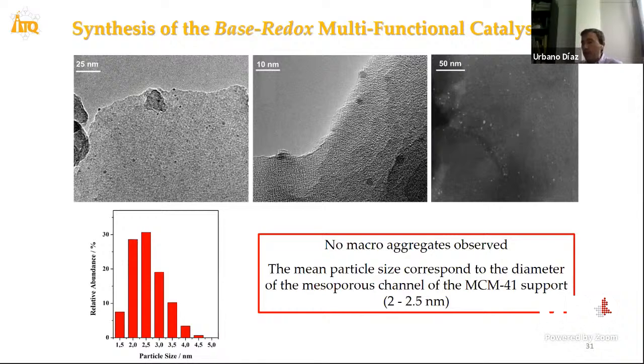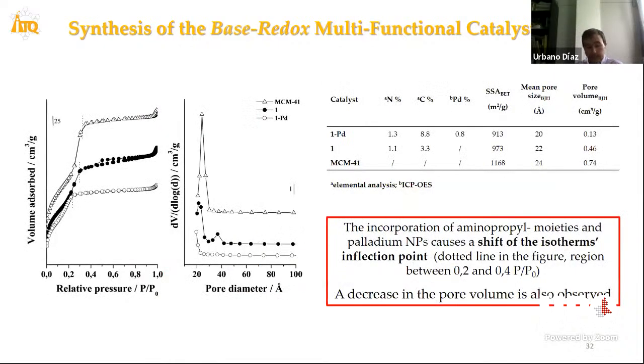in the internal pore volume of the materials. The characterization of these solids by nitrogen adsorption-desorption measurements confirms that from the isotherms it's possible to observe a shift of the inflection point to lower relative pressures, confirming the partial reduction of the internal pore volume, and the presence of these palladium nanoparticles in the internal pores. And also, logically, a decrease in the pore volume is observed.